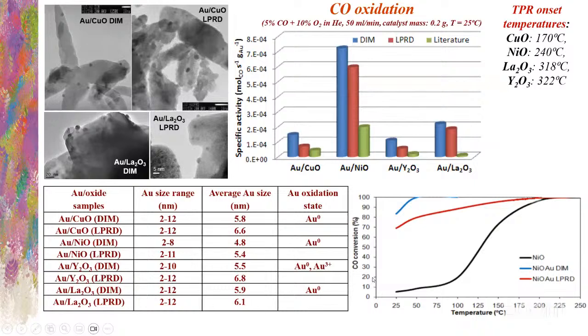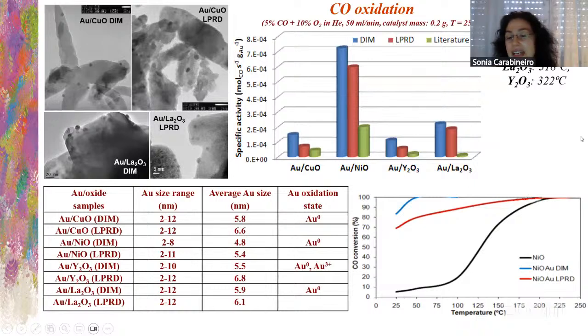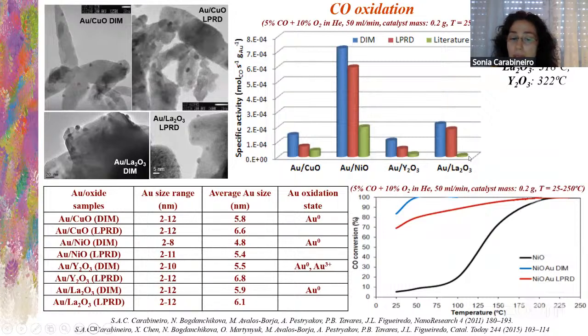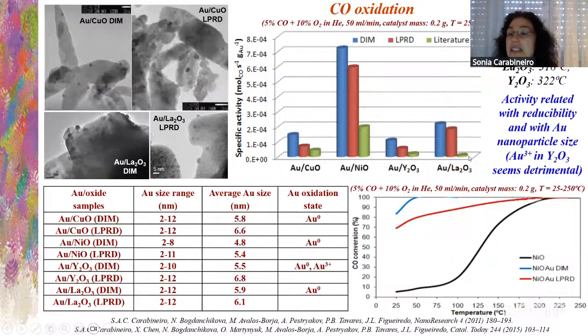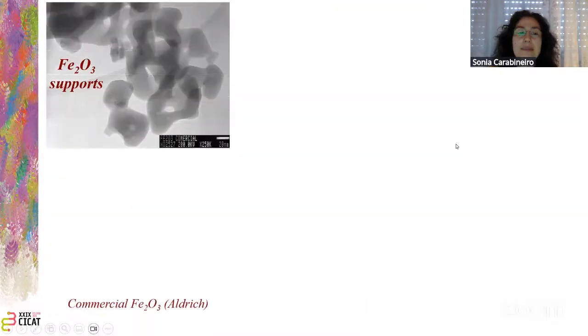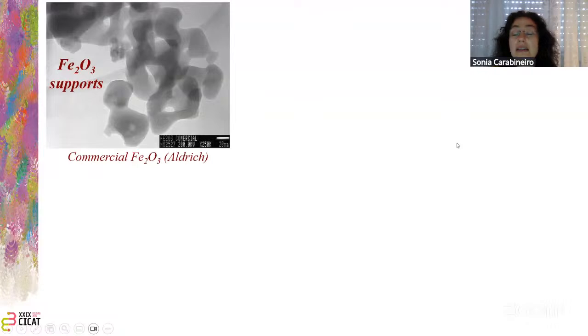This is for nickel oxide. You see here at different temperatures. This is just at room temperature, the specific activity. Here is at higher temperature. So we see that the activity is related both with the nanoparticle size and also with the reducibility, with gold 3 being detrimental. With iron support here, for example, we have commercial iron oxide.